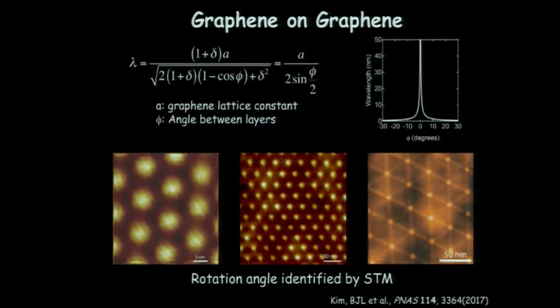And so we looked at this now just from a topography point of view. And so what you see here is we have the wavelength as a function of these 2 parameters here. Again, delta, the lattice mismatch between them, and phi, the rotation angle. And in this case, because we're using 2 layers of graphene, delta is 0. And so this equation simplifies to something which just depends on the rotation angle between the 2 lattices. And unlike the boron nitride, there is no limit to how large of a wavelength you can make. Right? If you make phi go to 0, this thing becomes infinite here. And so if we look at the wavelength as a function of the twist angle, it just diverges here at 0 twist angle.